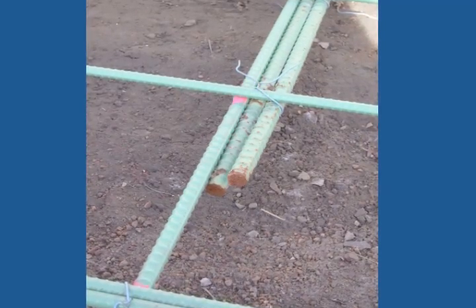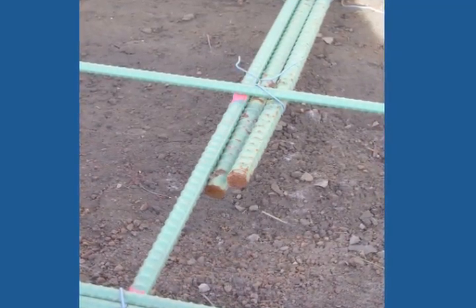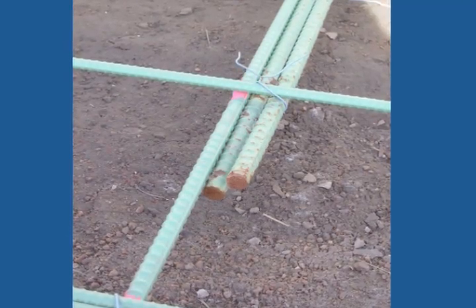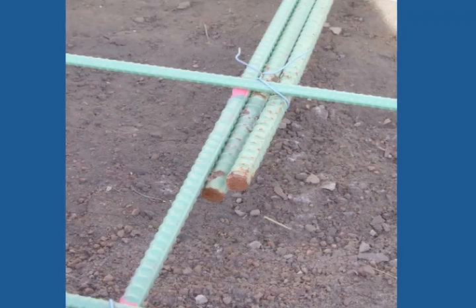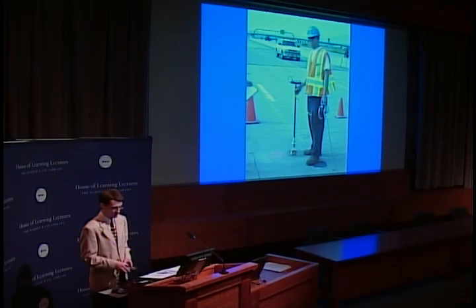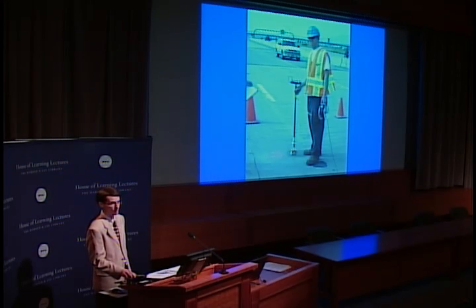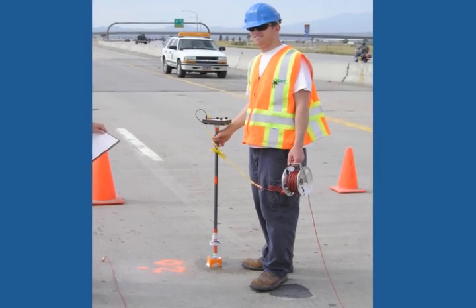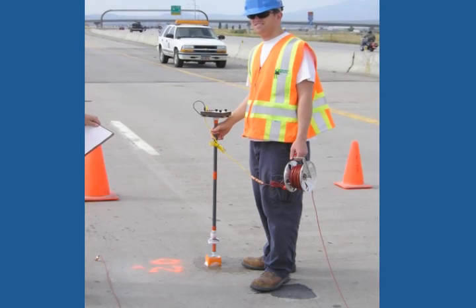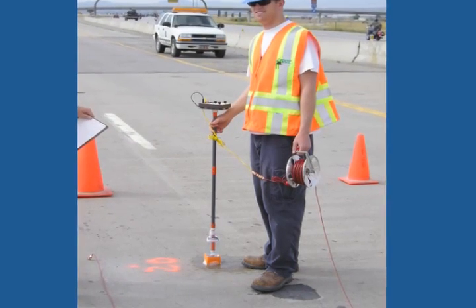Unfortunately, though, in too many cases, proper handling techniques are not utilized, and in fact, the ribs of the rebar are scraped. As the workers strike the tie wires down, they strike the epoxy coating of bars beneath, causing dings and other defects in the epoxy coating, and in many cases, the bar begins corroding even before the concrete is cast around it. In fact, in our field testing, we found that approximately half of the decks that we tested, which were known to have epoxy coatings, did not exhibit the properties of protection that we expected. In fact, they were as though no epoxy coating was present. This is unfortunate, but it emphasizes the importance of proper construction.